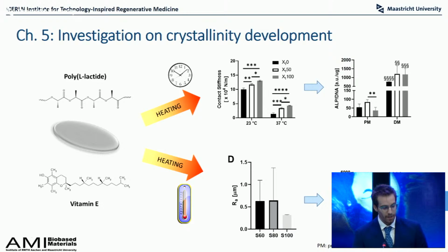The first type exhibited varying surface stiffness, but with constant roughness between the conditions. On top of these films, we then cultured cells that did not apparently exhibit any preferential commitment to osteogenesis. Therefore, the stiffnesses obtained apparently didn't seem to have any impact on cell commitment to the osteogenic lineage.